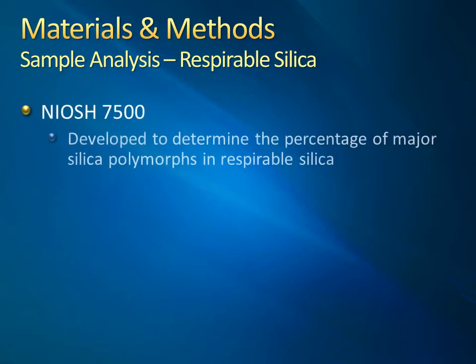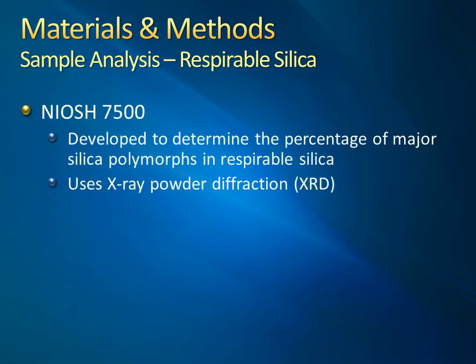The sampling of the air for respirable silica was performed by following the modified method NIOSH 7500. NIOSH 7500 method was developed to determine the percentage of major silica polymorphs in respirable silica, the quartz, cristobalite, and tridymite, using X-ray powder diffraction, or XRD. During the XRD analysis, X-rays are passed through a sample and are deflected as they pass through a crystal. From this information, the crystal structure and composition can be determined.